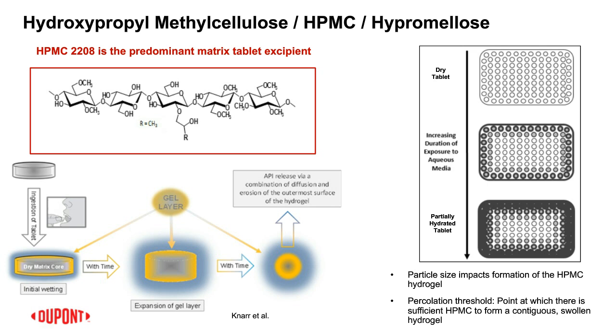And it's this matrix polymer hydrogel that's so critical for modulating the release of the drug from the tablet, okay? And again, I spoke to the fact that HPMC is a derivatized cellulose, right? So on those 2, 3, and 6 positions that I talked about earlier, there could be a methyl ether. There could be a hydroxypropyl ether. So this is a water-soluble polymer, and that water solubility enables that hydrogel formation. But first and foremost, you really have to have that nice percolating uniform lattice of those particles throughout the matrix tablet. So thanks for that segue.